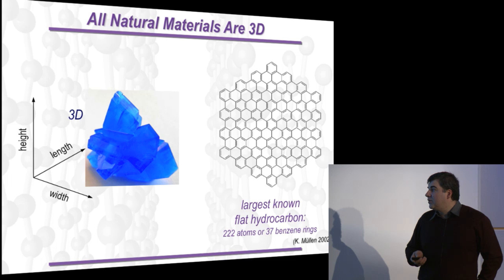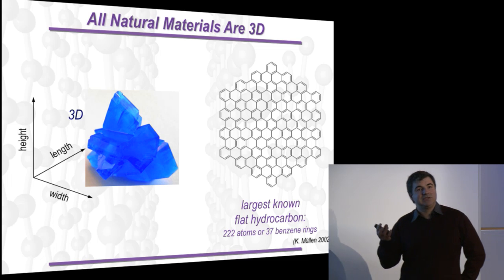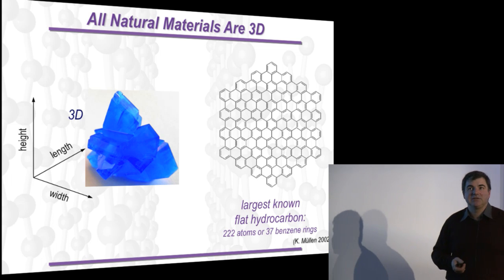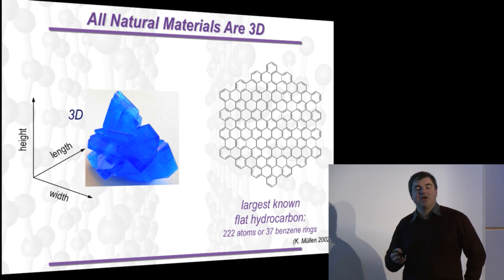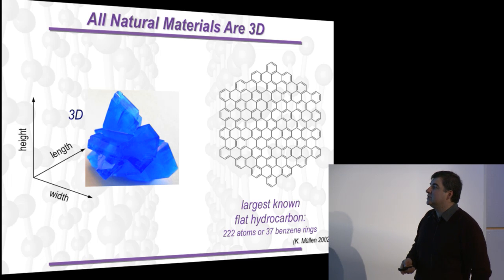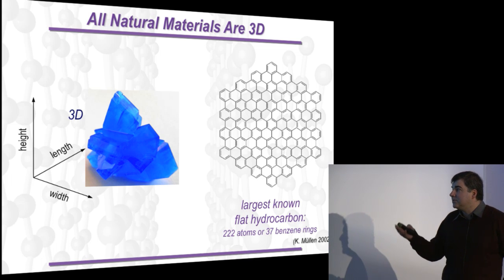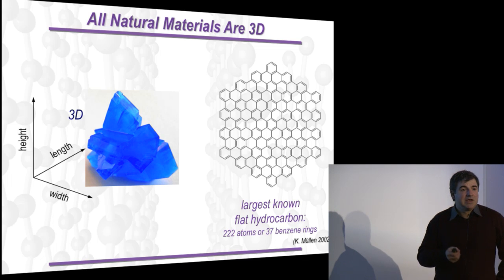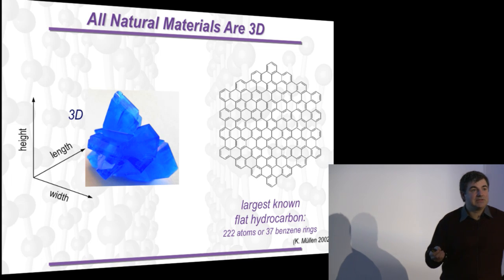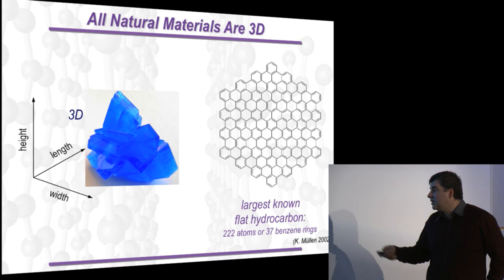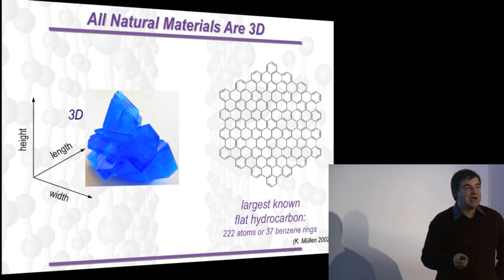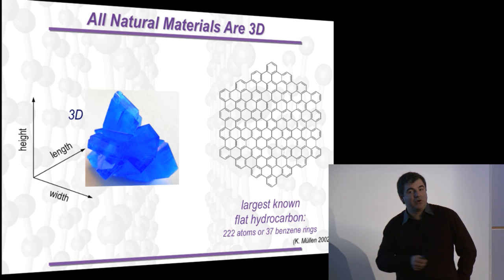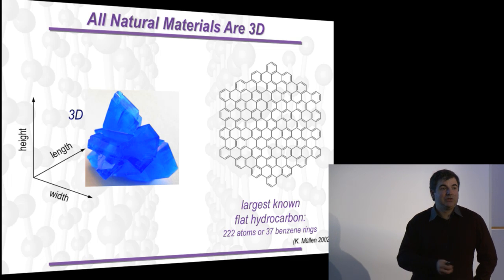Well, the solution is quite simple. You have to start with a three-dimensional object. So you grow this three-dimensional object like graphite at high temperature, and then you use low temperature and try to exfoliate it and slice it into individual planes. And it's known that graphite is quite easy to slice into quite thin platelets. Those are the SEM images of those, but you do it at home every time you use a pencil, because when you draw a line on a paper with a pencil, what you do is exfoliate graphite, you leave a trace of exfoliated graphitic particles.